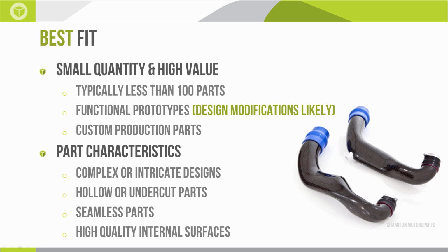What are the part characteristics? So we meet maybe the correct criteria above. When does it still make sense? Complex or very intricate designs. So we're obviously not going to be printing a cylinder alone and doing a soluble core on that because a cylinder wouldn't be trapped. So more complex and intricate designs where you would have trap patterns. If you need a hollow or undercut part, any part that's going to be undercut kind of ties into the complex situation there. If it's a design requirement that the part needs to be seamless, it might make sense. And also we need high quality internal surfaces. You'll notice a lot of the examples that I show today are of manifolds and piping where there's going to be internal flow. And it makes the most sense in those situations because the internal surface is actually the surface that matters most in order to maintain good flow qualities.